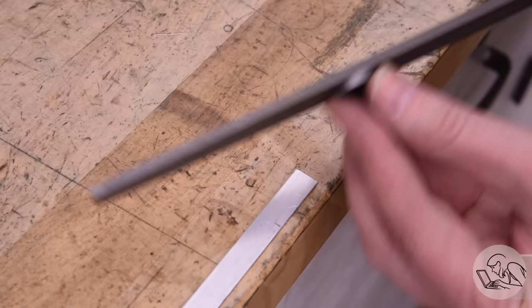Tempering this way is not just cool and convenient. There's a very good reason for doing it. Twist drills, for example, are typically tempered this way because you want the cutting edge to be as hard as possible, but you want the shank that goes in the Jacob's chuck to be softer. That's because you want it to be a little bit flexible, so the drill won't shatter if it's wandering a little bit, and also you want the Jacob's chuck, which is very hard, to be able to grip the shank of that drill, so you need the drill shank to be softer.